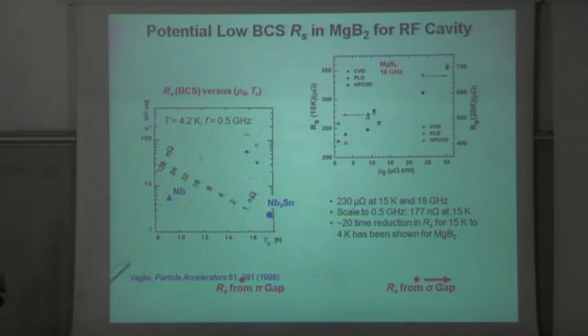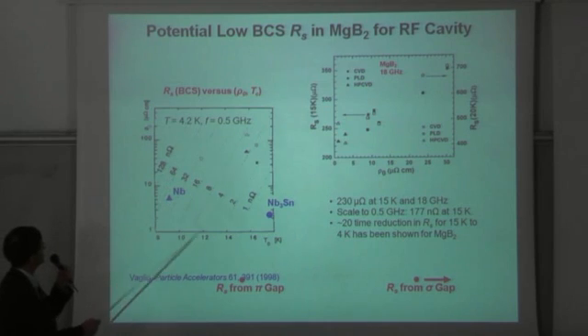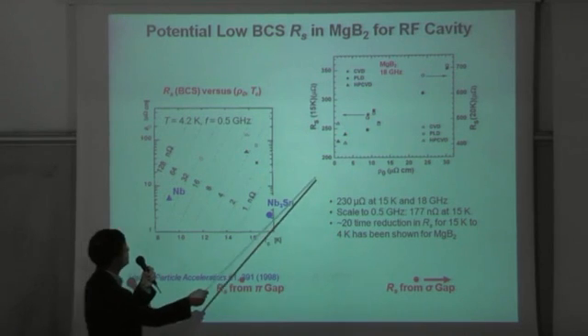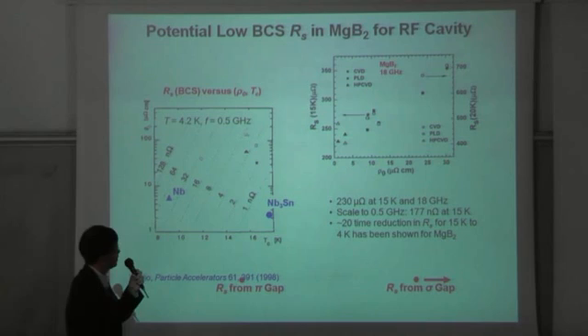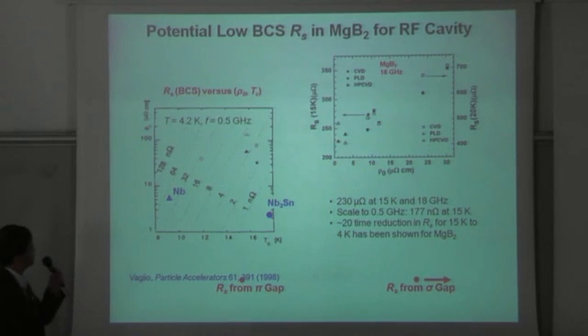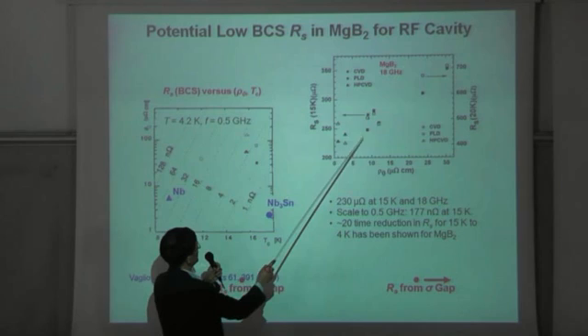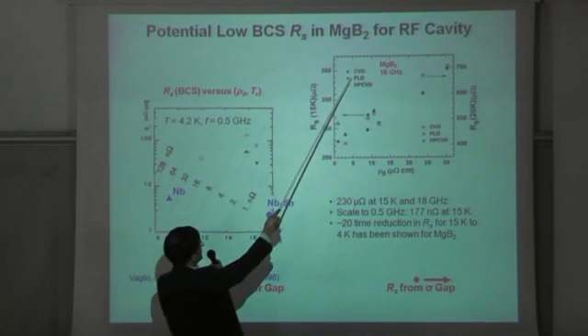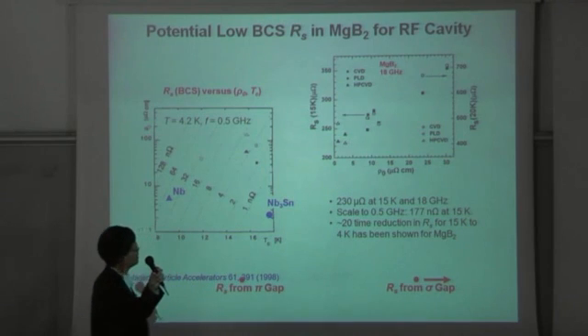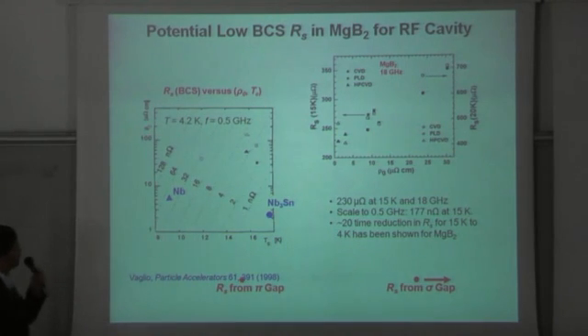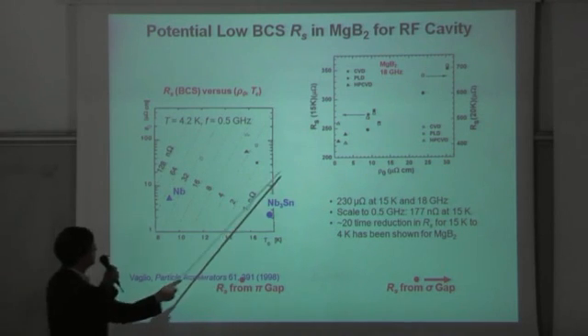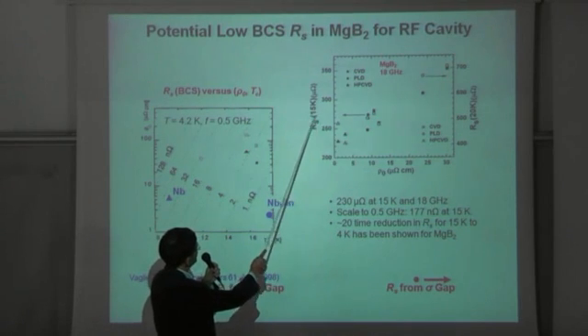So this is just some theoretical prediction from the BCS surface resistance. And here is the result of a dielectric resonator measurement that has our films, which is marked by HPCVD, these triangles, as well as films from other sources that the group at Jülich measured. And so this plot includes two sets of data. One is for 15 Kelvin, and the other is for 20 Kelvin.